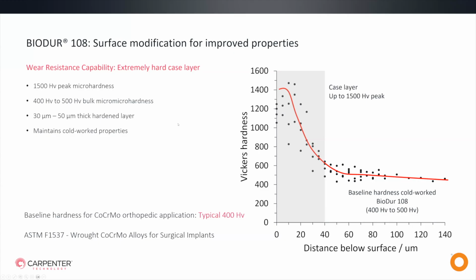But in doing so, the process creates this thin, hard case skin that's typically 30 plus microns thick, as I mentioned, and has a peak hardness around 1500 Vickers, or again, 70 plus HRC. So this really drives the wear resistance capability much higher, beyond what I shared in the comparison to cobalt chrome, beyond what the material's bulk capability would be, while maintaining that corrosion resistant, ductile, and fatigue properties of the base material.